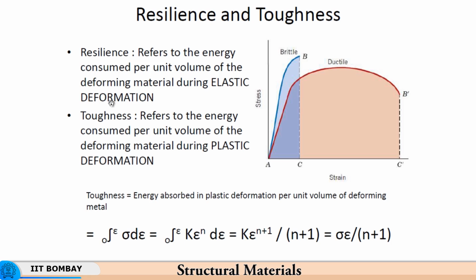So, E into epsilon will be sigma, and so E epsilon d epsilon will be for the elastic regime. For the plastic regime you have sigma equal to k epsilon to the power n as the expression for sigma, and so you get k epsilon to the power n plus 1 upon n plus 1 as the energy stored in the material due to plastic deformation. So, sigma epsilon upon n plus 1 is the energy stored in the material due to plastic deformation. So, what does it mean? It means the dislocation density that is increased. So, you have spent certain amount of energy on plastic deformation, some energy got converted into heat and some energy got converted to increase in dislocation. So, increase in dislocations means that the energy was used for increasing the dislocation density in the material as the material work hardened and resulted in